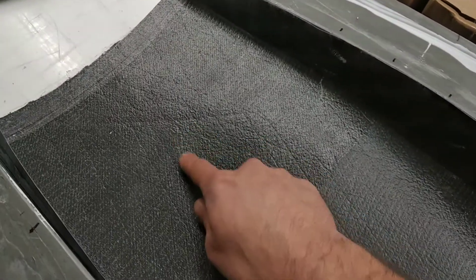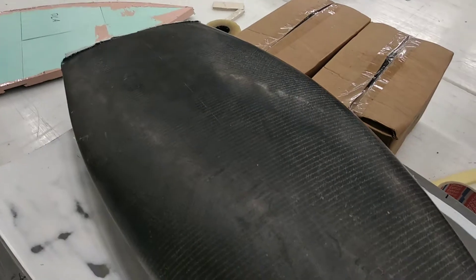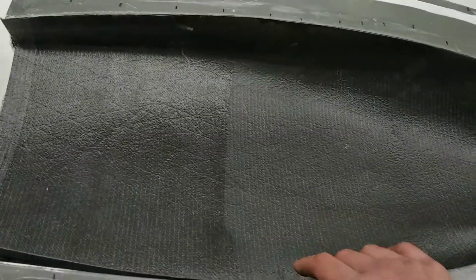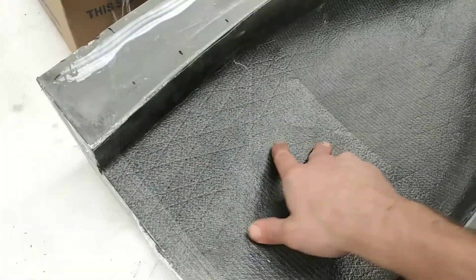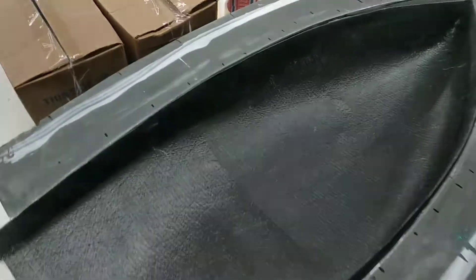What you can also see are these diagonal lines — these come from stitching or knitting the fiber together, which basically prevents fiber disorientation, but they are not shown on the boat surface. The boat surface is just a single layer of resin inside the mold. To achieve that you just brush in some resin with thixotropic powder like aerosil, let it cure around about three or four hours, then apply a new layer of fresh resin and then you can add your first layer of carbon fiber. This will give you a super light finish and still a water-sealed and air-sealed outer skin.